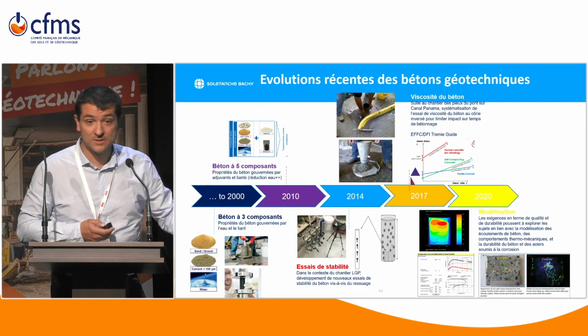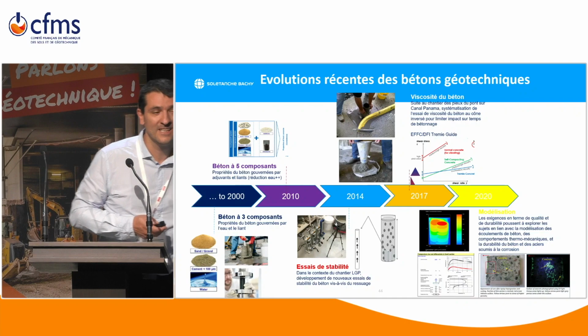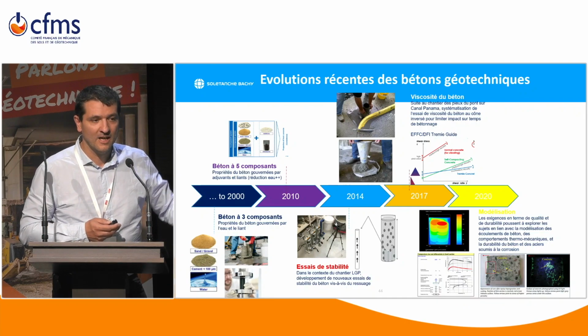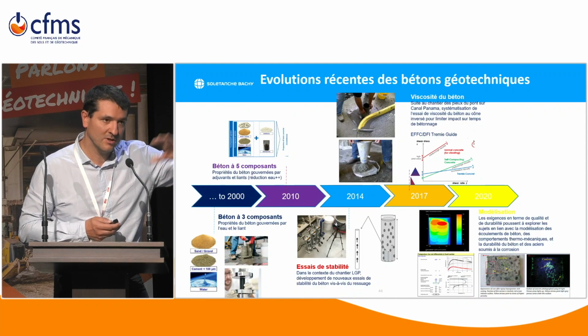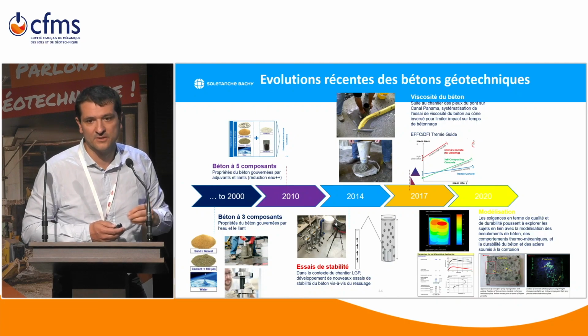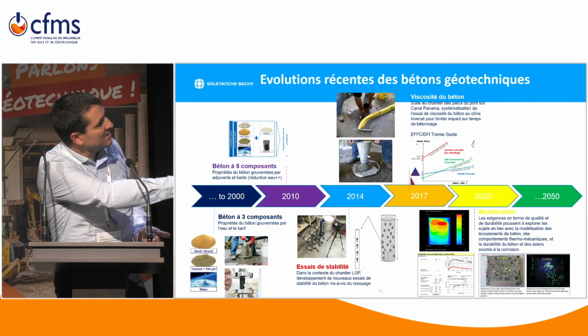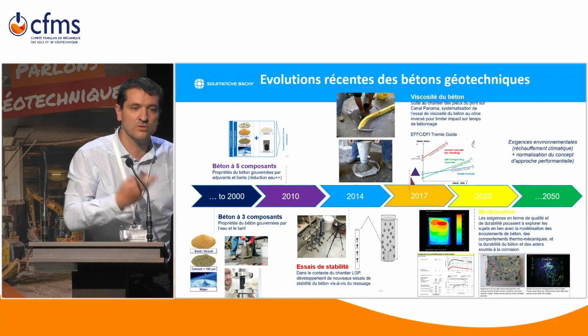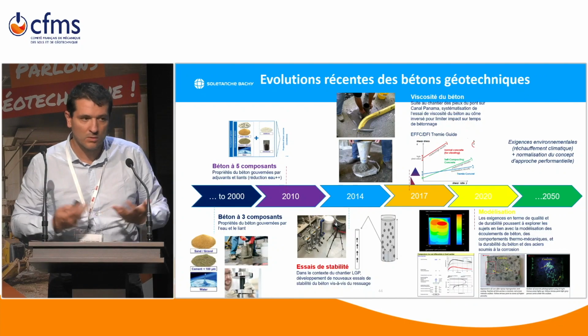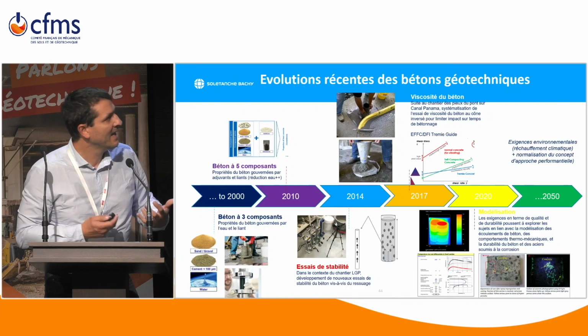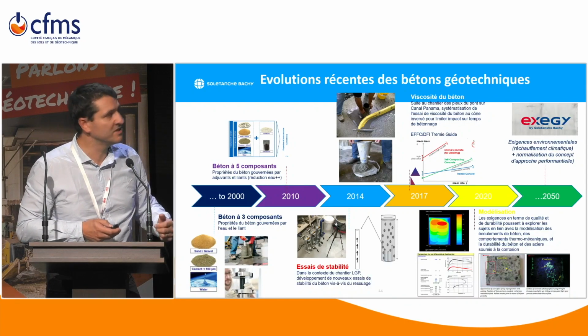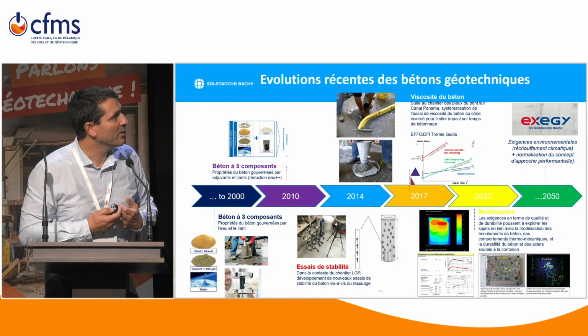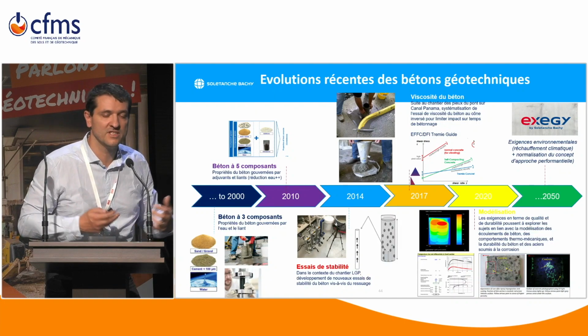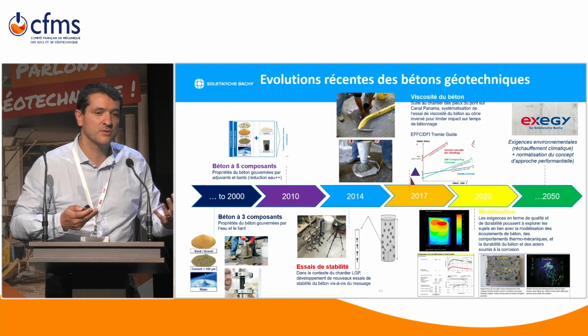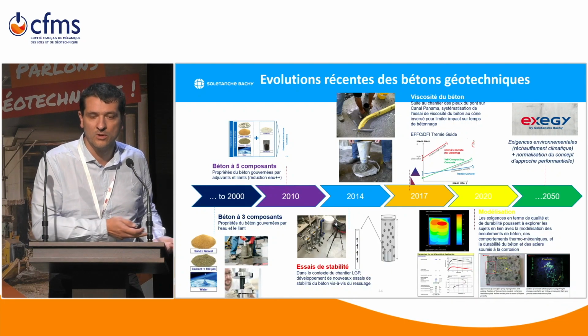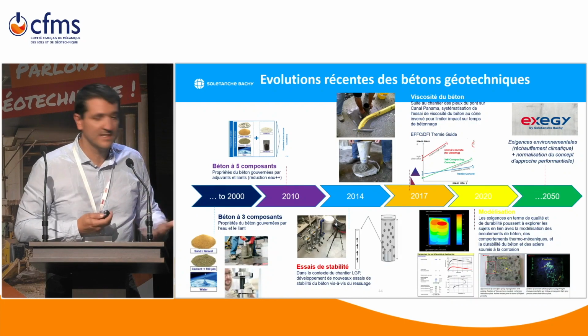Last but not least, our challenge, because we are following the trend in concrete, is a performance-based approach, meaning designing concrete not according to a prescribed mix from the standard, but based on durability indicators. And this is the next step, going with the transition to lower carbon emission of concrete. So we have a role, we need to look at that in geotechnical concrete. That's why, for example, companies like Soletanche-Bachy have their policy or their way to engage in that. So Exegy, for example, by Soletanche-Bachy, is all the consideration we are taking in the mix design of the concrete in order to optimize and lower the CO2 impact by replacing Portland cement with other additives.